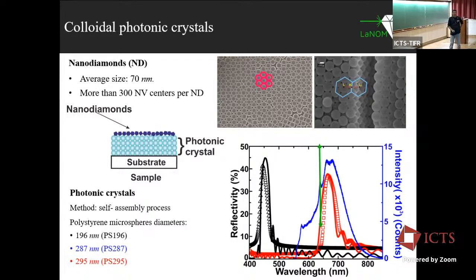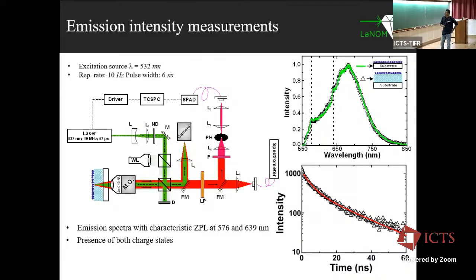And what is more important for photonic band gaps or photonic crystals is the band edge effects. We can see that in this photonic crystal, the band edge is close to the zero phonon line. So we expected a cavity-like effect at these band edges, even though there is no spatial cavity in the system. We developed a very simple experiment long back to collect the emission spectra.